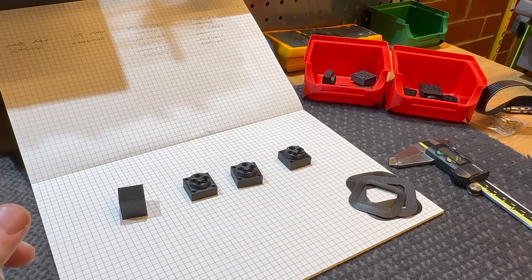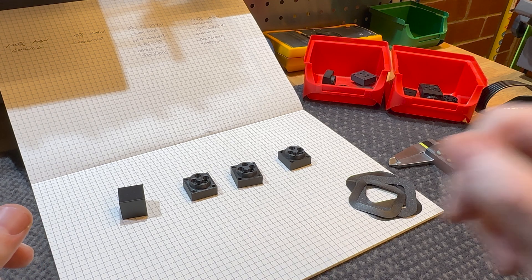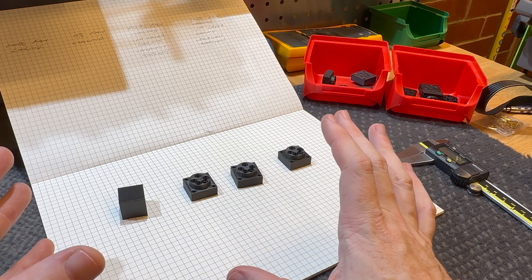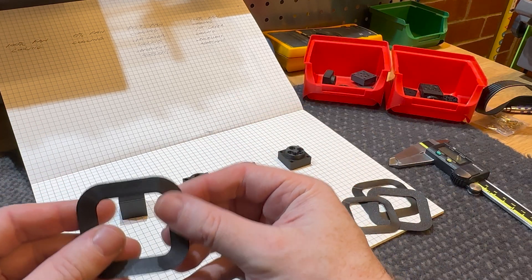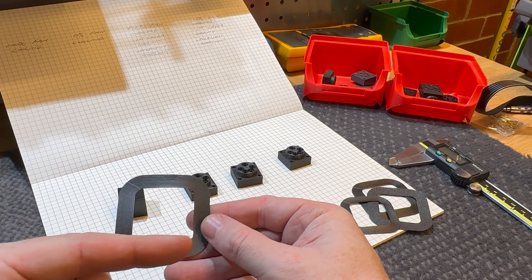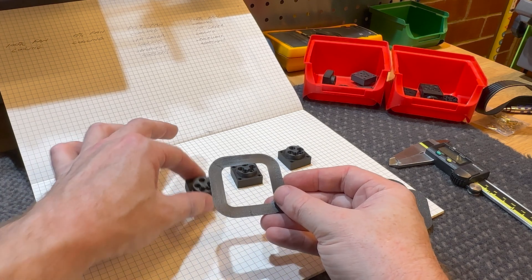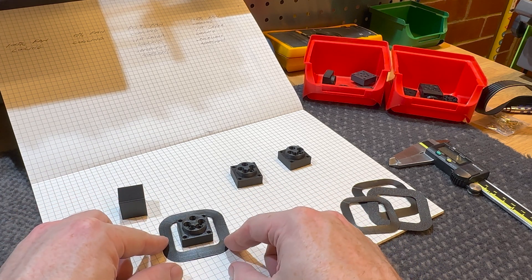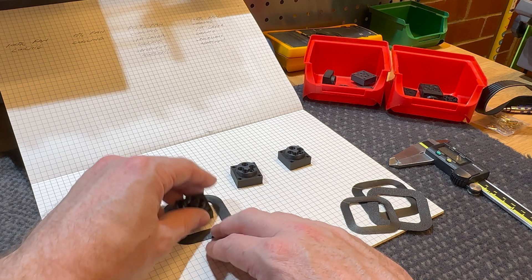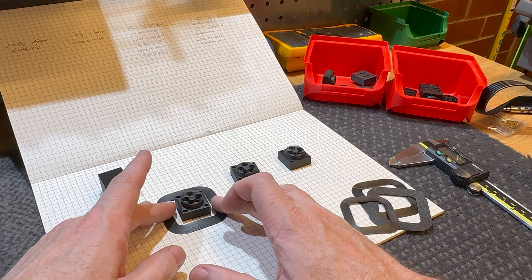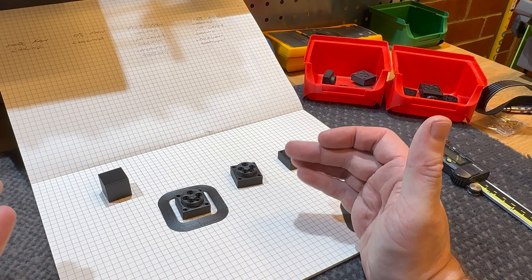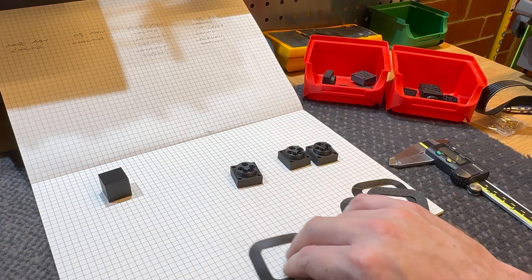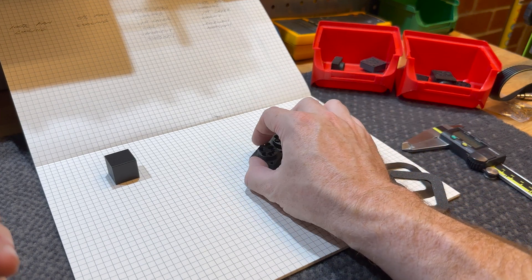Now, the Snapmaker, I don't know if there's a G-code that could do a purge line like a really thick one, so what I resorted to doing instead is I did a skirt, but I did it 15 passes, so it's quite a big skirt that is laid around the part. But that purges a decent amount of filament to get it ready for use, because even the filament in the Bowden tube is going to absorb moisture, so you need to keep that in mind.